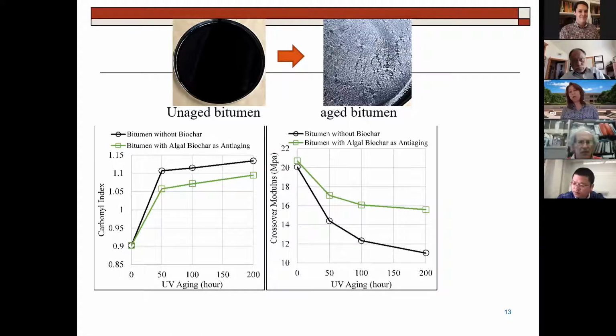Both curves are indicators of aging. Don't worry about what is on the vertical axis as the indicators. It just shows you it's changing, right? Over the x-axis is time. So I'm just showing you how the asphalt changes in certain properties. And then what we have done, we added some functionalized carbon here, which is made from algae. And you can see the green. So yes, it still goes up, maybe a bit less than the black. The carbonyl goes up, but not as high as this, and it flattens. Same thing with crossover, it goes down, but not as bad as this, and then it flattens. So if I can stop this change, if I can stop it so it is flattened forever, that means I stop aging, at least in terms of rheology. So I say my material is stopped here and it's going to continue forever going that way.